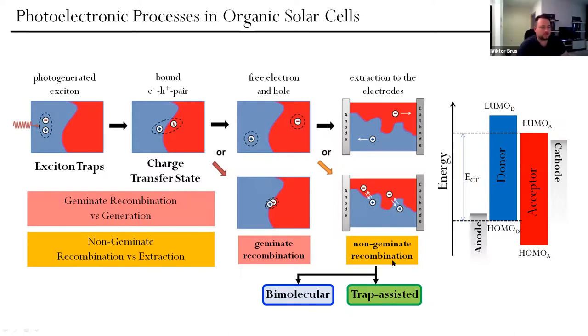There are so-called non-geminate recombination losses, when electrons and holes originating from different excitons meet each other on the way to cathode and anode, or at the interface, and recombine. So this non-geminate recombination can be split into two mechanisms. First, bimolecular recombination, when we have band-to-band recombination, and we cannot avoid this because if we can absorb light like a photon and generate an electron-hole pair, it means that it should be possible to have a reverse process and get recombination of the electron-hole pair and get a photon as a result of radiative recombination.